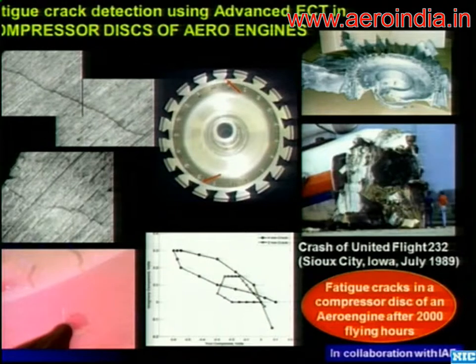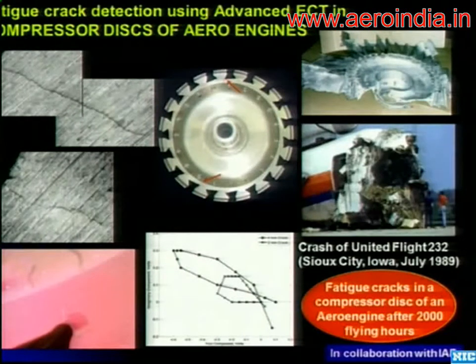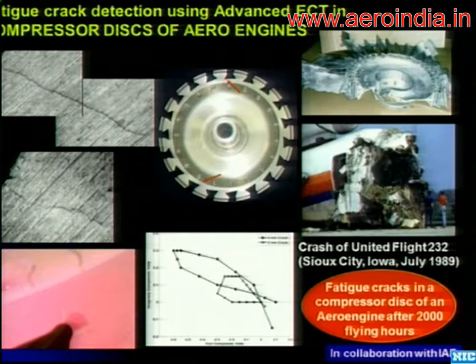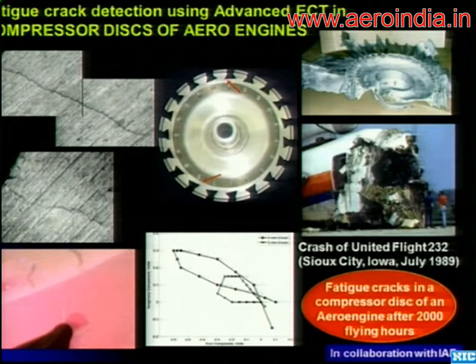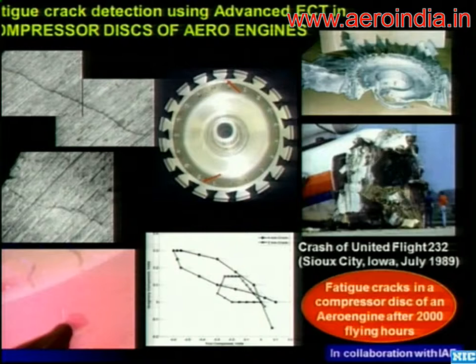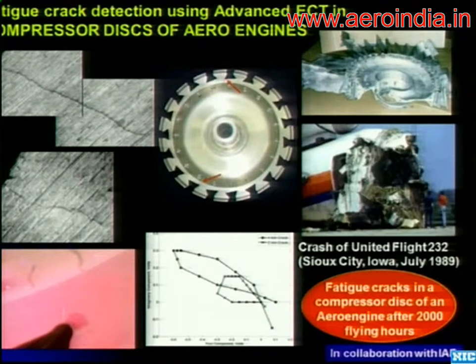Taking a classic study where damage tolerance, mean time between inspections, and failure prevention are demonstrated: the compressor disc. Such failures have been taking place in India. When we analyzed this, what we identified is that the inspection procedure given by the OEM would be able to detect a surface crack length of around 4 millimeters. If a crack of 3.5 millimeters is missed at one inspection, by the next inspection it would have grown to the critical crack length, causing catastrophic failure.